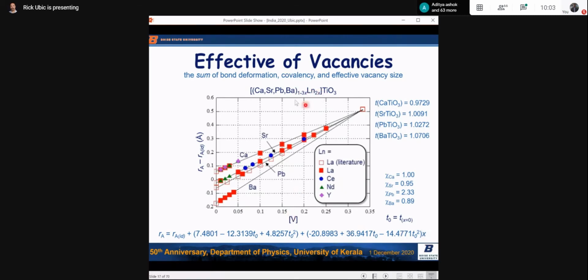It's identical when we formulate this way, x is vacancy concentration. So this bottom equation is the important one. The A site size has 3 components. It has the Shannon, whatever Shannon says it's supposed to be, the ideal size. It has this term, which comes from this intercept, which we call a bond deformation.